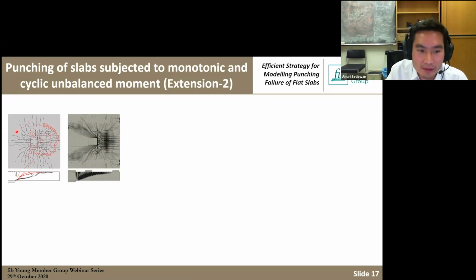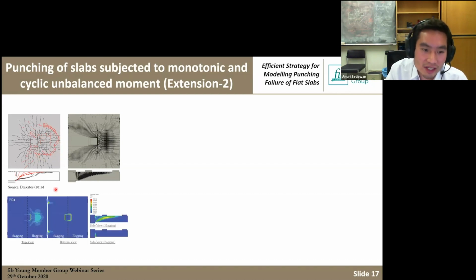So for extension 2, for slabs with unbalanced moment, the situation is also different. We see here a slab tested at EPFL as well. With a monotonic eccentricity, you can see that the eccentricity goes to the right of the column. So you can see the tangential crack actually only forms on one side. We did some 3D solid analysis as well to confirm that. Yes, we can see that the maximum principal strain, which is tension, is concentrated only in the hogging region, where the shear stress from the unbalanced moment is added to the shear stress from the gravity load.